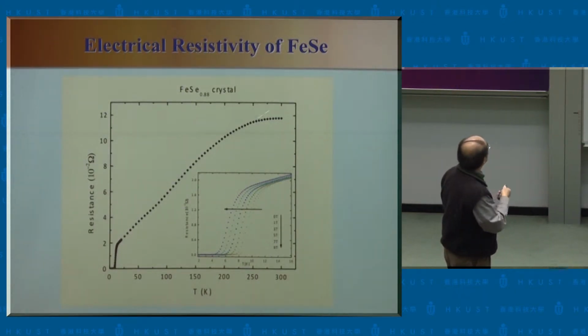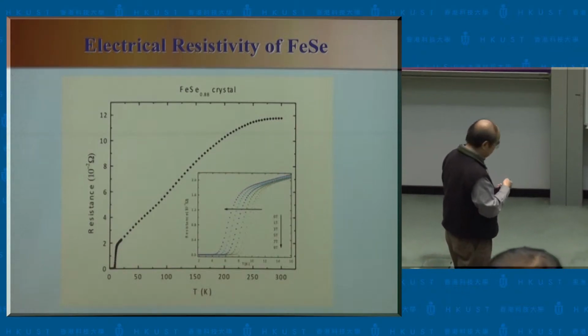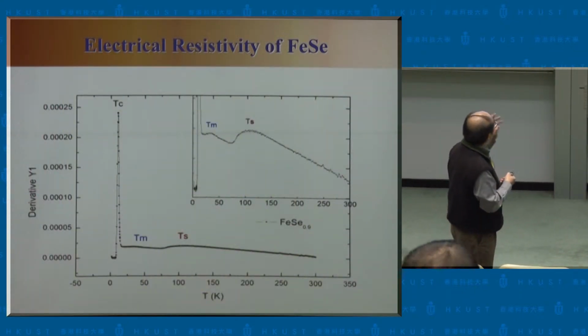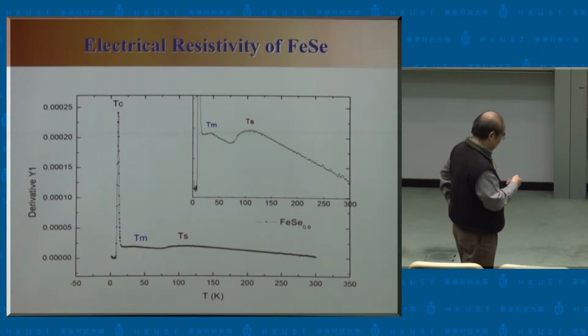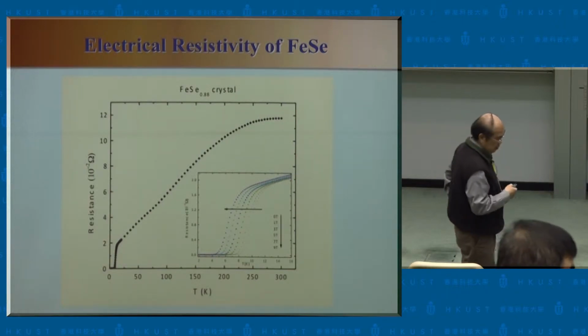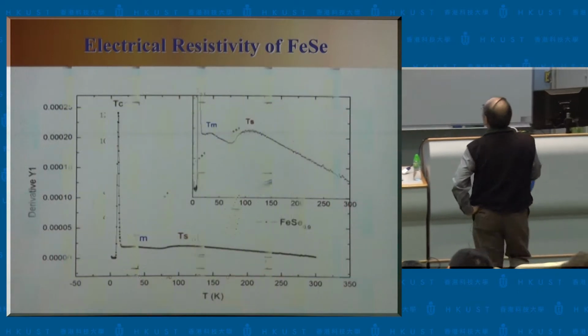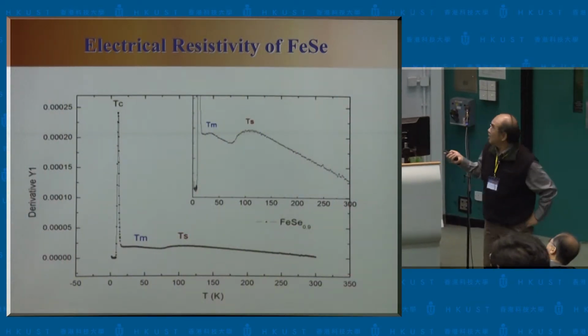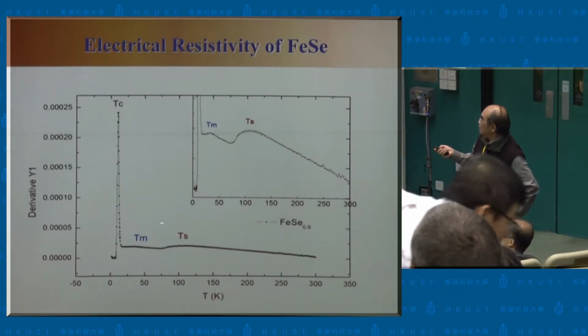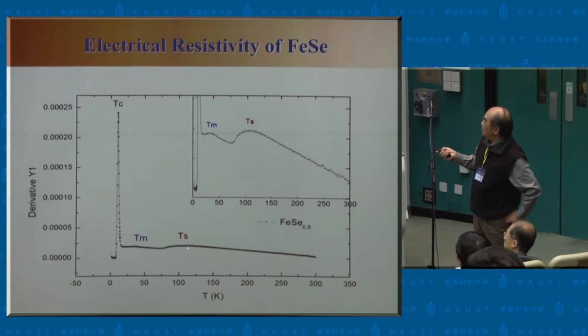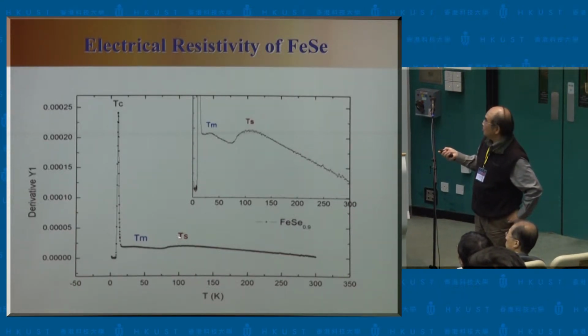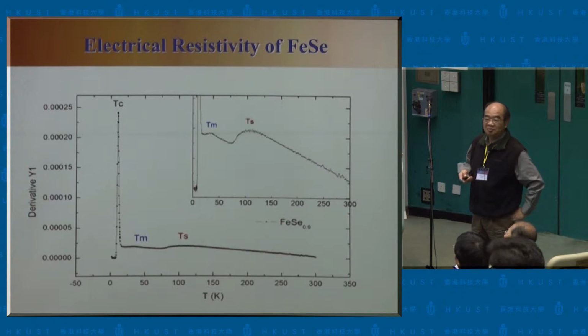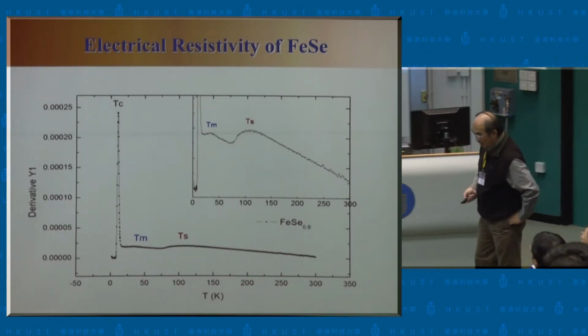before I do that, of course, there are a lot of interesting features in terms of electrical resistivity in this particular selenide, which I'll come back to in more detail. But if we look in more detail, by analyzing the data here, by taking the differential, immediately you see some very interesting features. One, of course, is the superconducting transition. Then there is a small kink around 100 or 90 Kelvin, and we clearly associate that with some kind of structural transformation. I'll come back to that. In fact, there's one interesting anomaly around 40 K. Whether this is related to that high pressure phase.